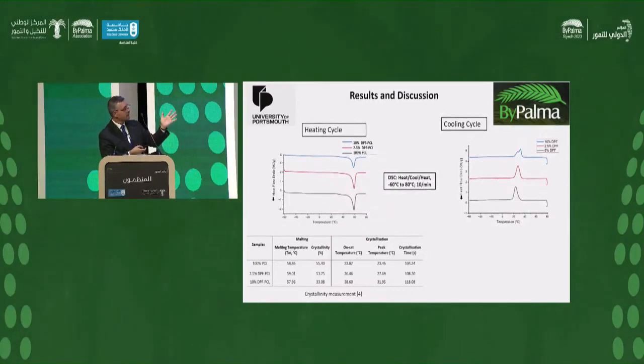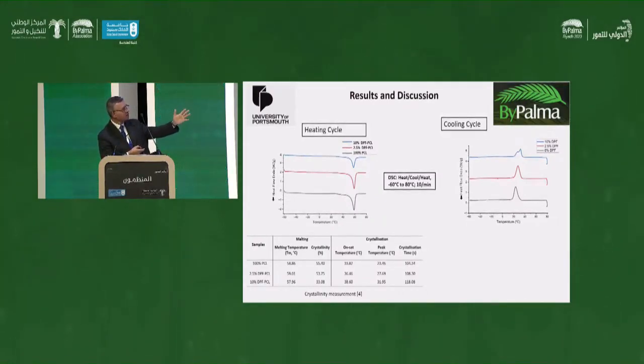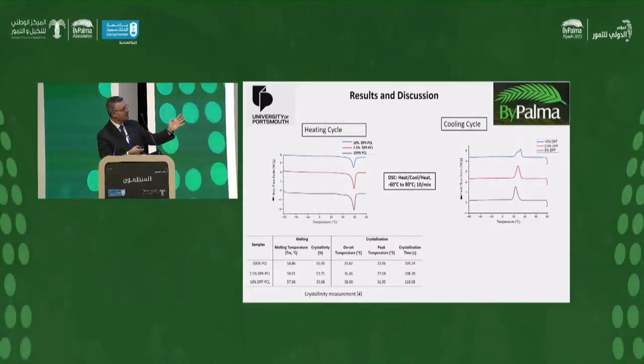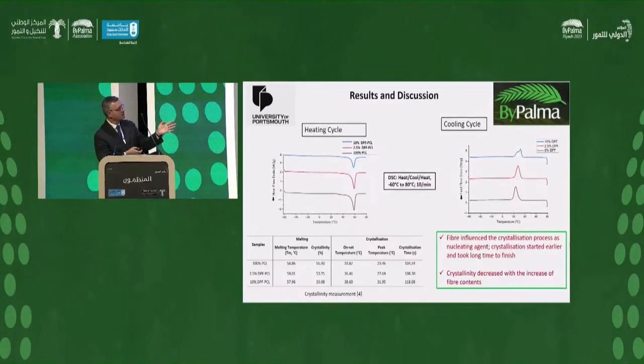In terms of peak temperature and then onset of degradation, you can see the temperature has increased with the inclusion of date palm fiber. And then crystallization time has also increased. So with that, you can see the shift in the peak of this result. So the fiber has influenced the crystallization process, and crystallinity decreases with the increase of fiber content.